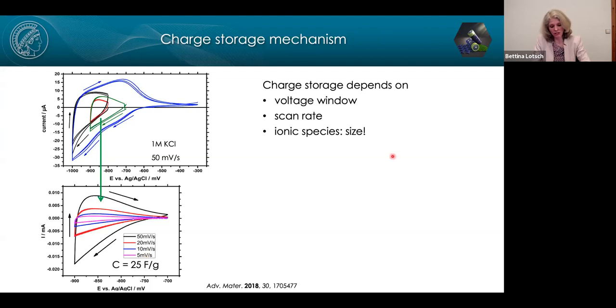What is also interesting is that the ionic species in the pores really contributes to the ability of the system to store charge. And that is also not too surprising because we believe we need the screening of the electronic charge carriers. And so if the cations are too large, too bulky to enter the channels, then we don't see charge storage. So for example, for tetrabutylammonium cations, we don't see charge storage. So the size of the ionic species matters.